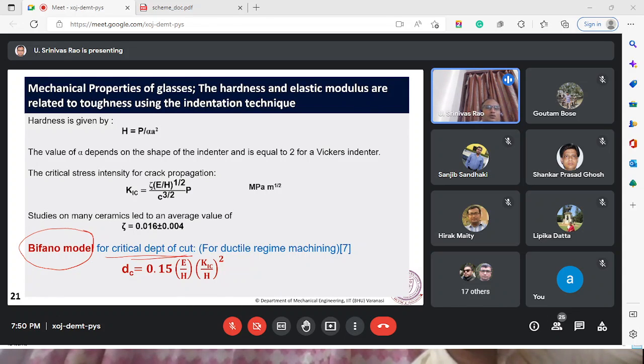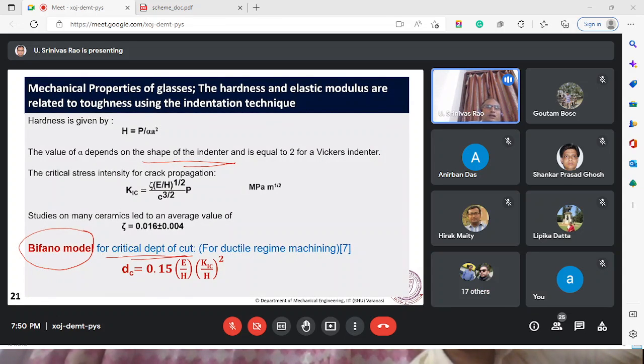Okay. So normally indentation is done for hardness test. So based on the shape of the indenter, we have the hardness value calculated, and that can be used to find out the critical stress. Okay, and fracture toughness, we find that in which this zeta value is given. These are all empirically obtained.